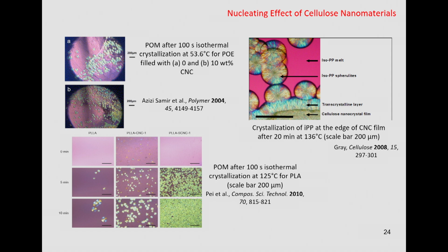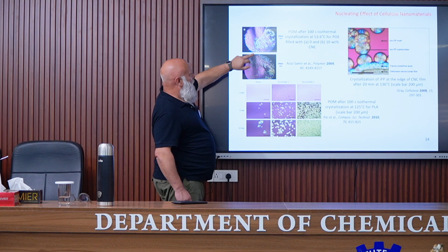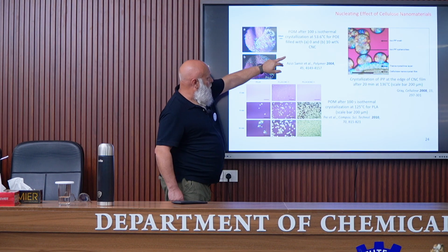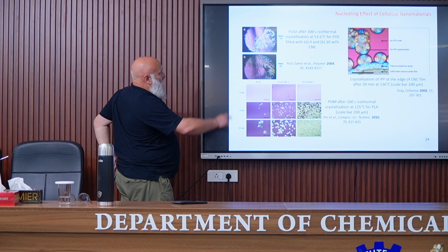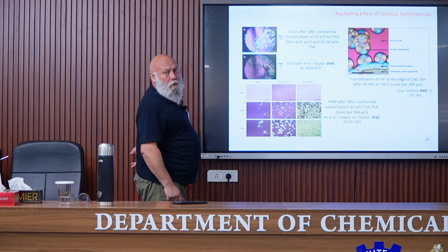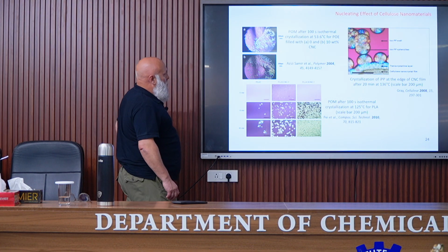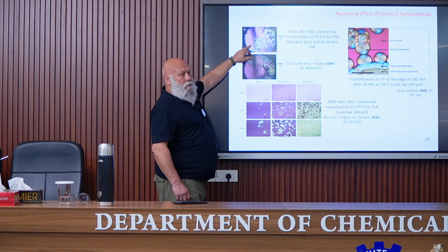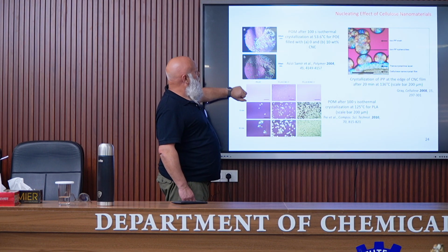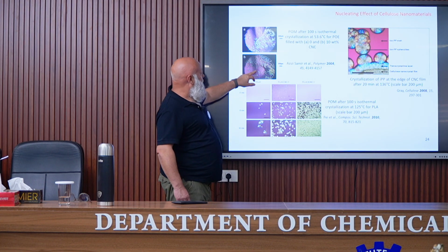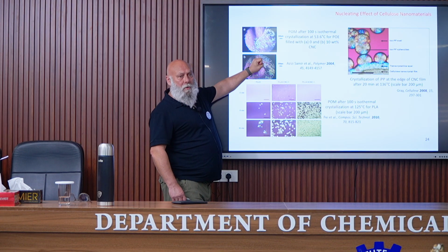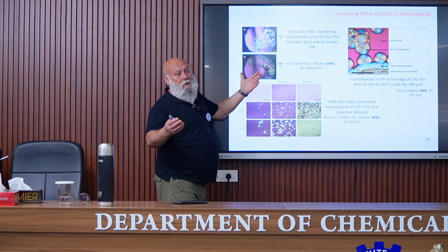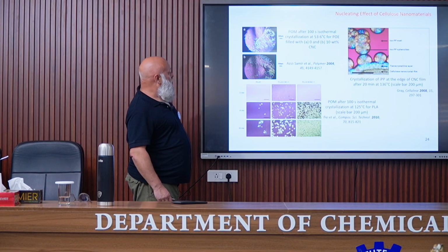This is polarized optical microscopy after 100 seconds of isothermal crystallization. This is for PEO at 53 degrees, so the melting point is around 60 degrees. The pure matrix and with 10% nanocrystals. We can see that the crystals are smaller, but there are more because nucleation was easier.